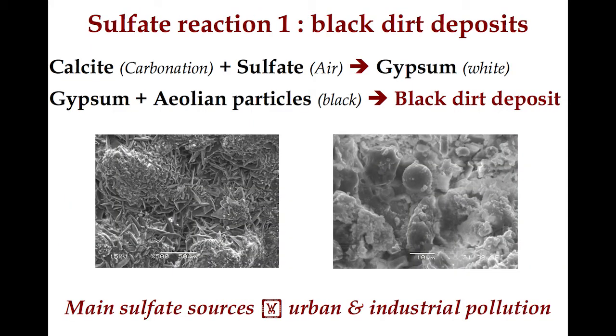Now, the sulfate reaction, there are two sulfate reactions. The first is the formation of black dirt deposits. So the calcite, given by the carbonation, reacts with sulfate in air to give gypsum. Gypsum is white. The gypsum reacts with aeolian particles, which are black, to give black dirt deposit. You can see here gypsum crystal and fly ash particle. So the main sulfate sources are urban and industrial pollution.